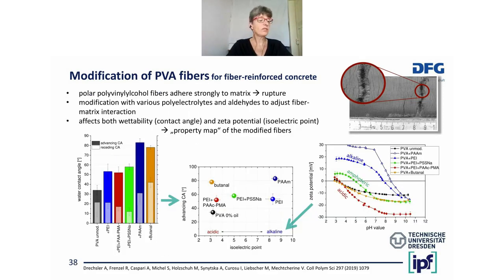We again tried to do this by adsorption of polyelectrolytes, by acidic and alkaline polyelectrolytes, but also by chemical bonding of aldehydes. And we studied many properties of these fibers, but especially the contact angle in water that is shown at the left side and the Zeta potential shown at the right side. And again, you see how the adsorption of the polyelectrolytes changes the Zeta potential and the isoelectric point of the fibers.